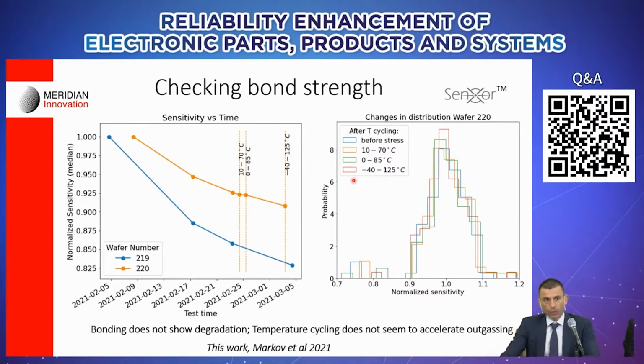So what we see here, I report just normalized values, but basically you have the control wafer, which is in blue, and the wafer that underwent temperature cycling. And so here at that point, 2 wafers are tested, and then 1 wafer undergoes cycling at 10 to 70 and is tested, then undergoes 0 to 85 and is tested, and then the extreme range of minus 40 to plus 125, and we measure again.